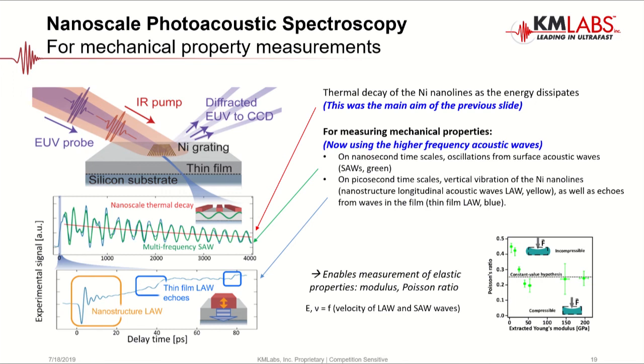But what's really remarkable here is that we can do this for films and structures that are even down to the nanometer length scale. And this is pretty important because when we're designing these kinds of nanomaterials, our classical physical characterization experimental tools don't really apply. They have certain assumptions or capabilities built in that dictate they need some amount of length scale or some amount of material to produce a reliable reading. But once you get down to these tiny length scales, that just doesn't hold. And so now this is really useful where we can use an optical technique and we can probe these types of effects leveraging the optical and mechanical interactions of that beam with the sample. And we can do it on really, really small things that aren't possible any other way.